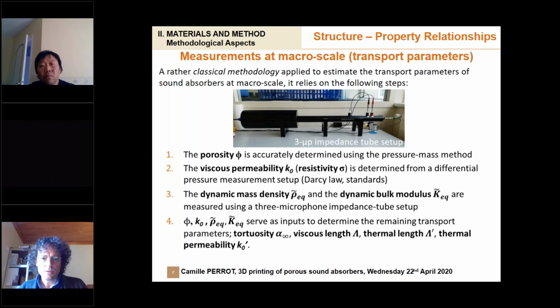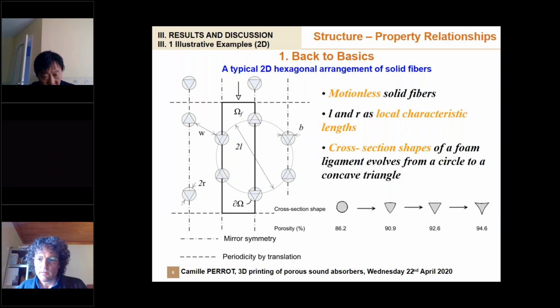So let's try now to give a few simple examples to get a kind of intuitive vision of microstructural features having a significant effect at the upper scale. Let's begin with a simple two-dimensional hexagonal arrangement of solid fibers. The wave is impinging the sample from one of the perpendicular directions, X or Y direction, and you have basically three microstructural features to describe this very simple structure. You have the fiber radius, you have the pore size, which is associated here to 2L, and you have eventually the fiber cross-section shape.